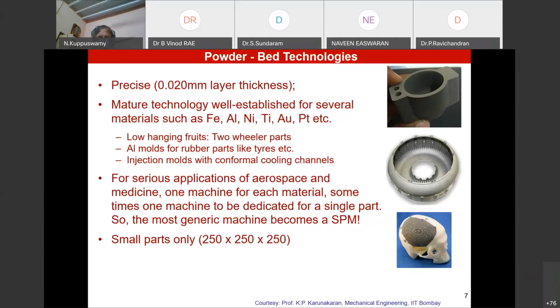The powder beds, as it says, the build zone is typically 250 millimeter cubed. The bigger it is, the more difficult it is to manufacture. Whereas in the case of laser cladding, you can have very long machines. There are multiple methods being used. Therefore, that's got a different scope. But you will never get a very fine part like the one in the picture here out of laser cladding. Because in powder bed, the part comes out almost ready to use.